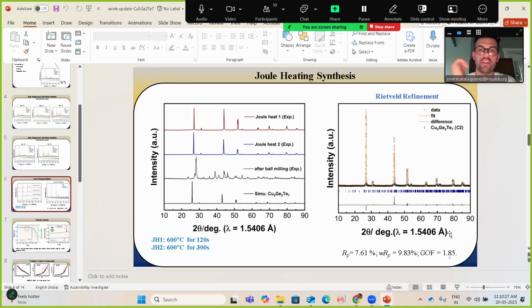Is there a systematic error of some sort that's possible? Jayant, you did the XRD yourself, right? The only systematic error that could be here is sample displacement. This is your stage. Unless your sample is perfectly parallel to your stage, there is a sample displacement, which is of the order of a few microns. This sample displacement is too large. Normally sample displacement is eliminated by using the same person for experiments, because we all prepare samples in the same way. My sample displacement for the Ag2Te stuff is constant.